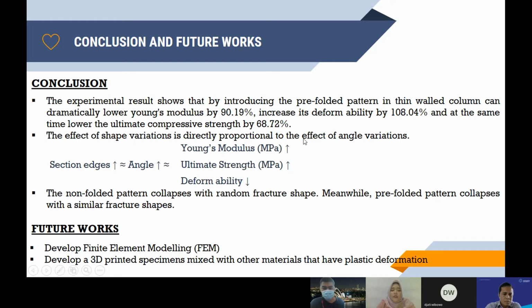The effect of shape variation is directly proportional to the effect of angle variation. As the section and angle increase, the Young's modulus and ultimate strength increase, while the deformability decreases. The non-folded pattern collapses with random fracture shapes. Meanwhile, the pre-folded pattern collapses with similar fracture shapes.